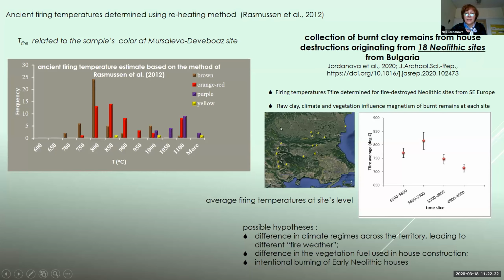from different parts of the territory, and summarize the data obtained about the firing temperatures, again obtained using the same method. And here you can see the final summarized data according to different dating periods of the different sites. And it's seen that the highest firing temperatures are obtained in sites which are dated in the early Neolithic times, with a progressive decrease in these temperatures. And I want to just point out that these are site averaged data. So we averaged all the estimations coming from the specific site.